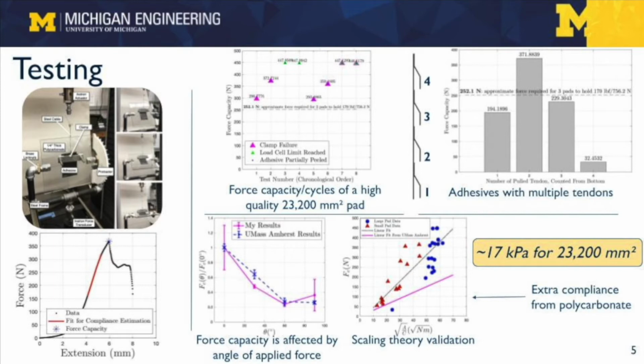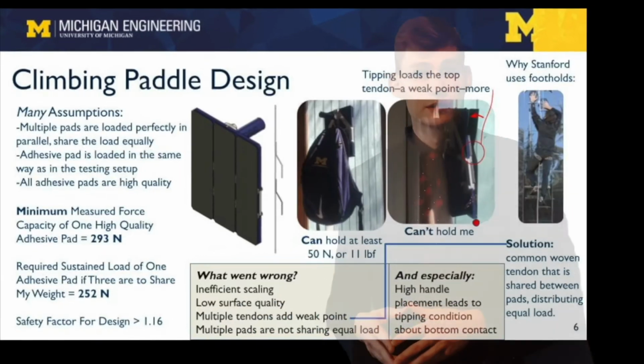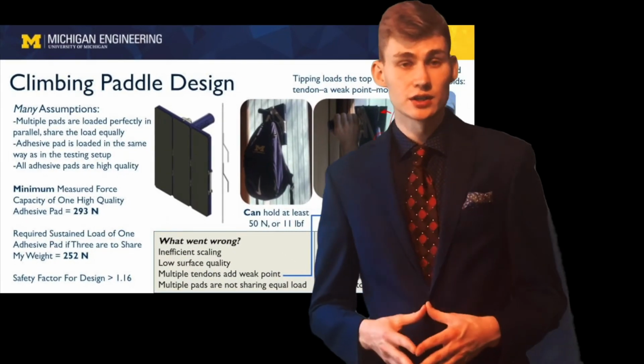Now in my experiments, I was able to create adhesives that only had a shear stress capacity of about 17 kilopascals with a pad area of about 23,000 square millimeters, a much lower performance than the adhesives from UMass Amherst and all of the other approaches for that matter. So there must be something fundamentally wrong with the way I have made them. Now on to the last part of this project, human climbing.